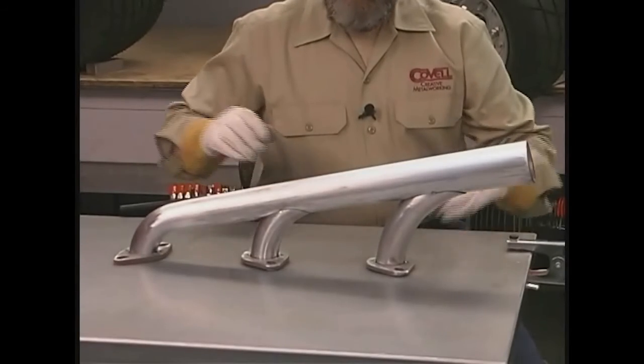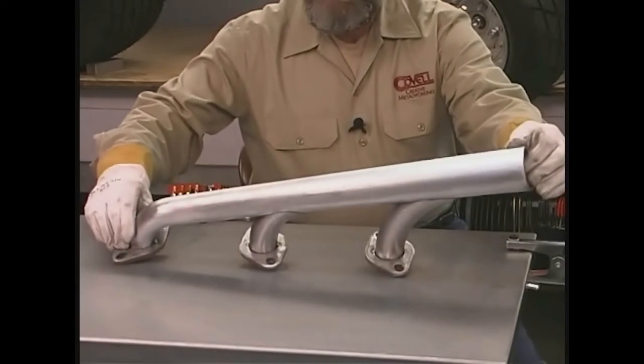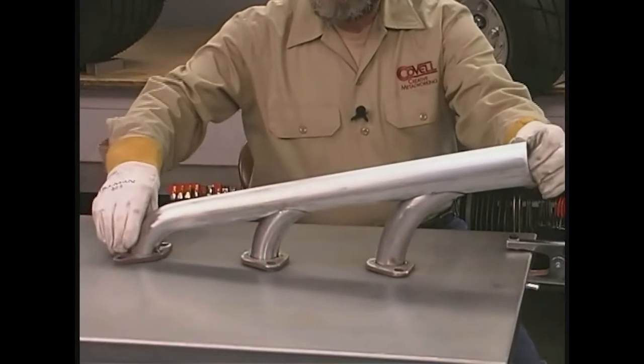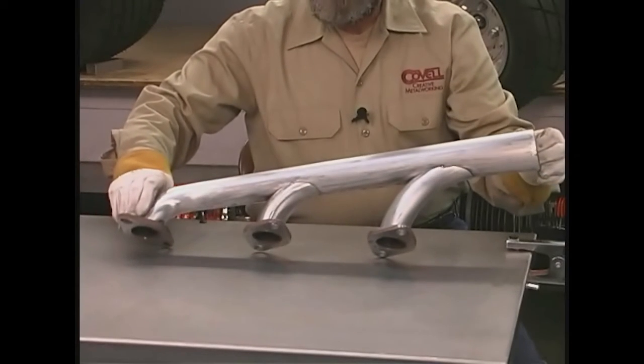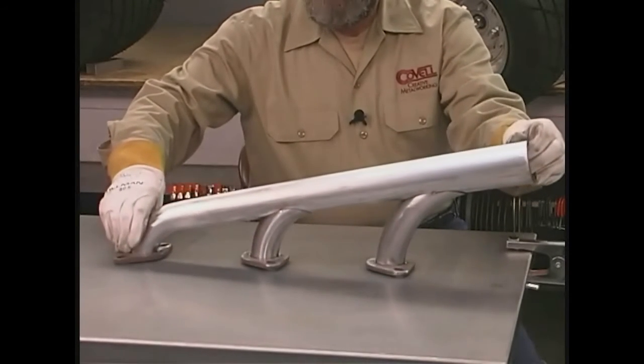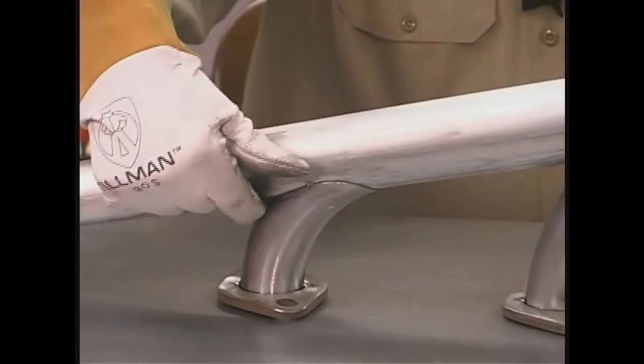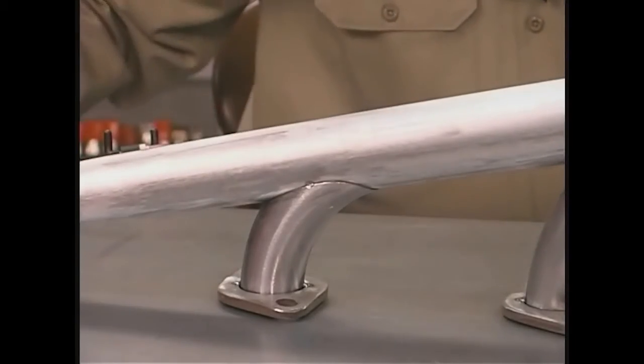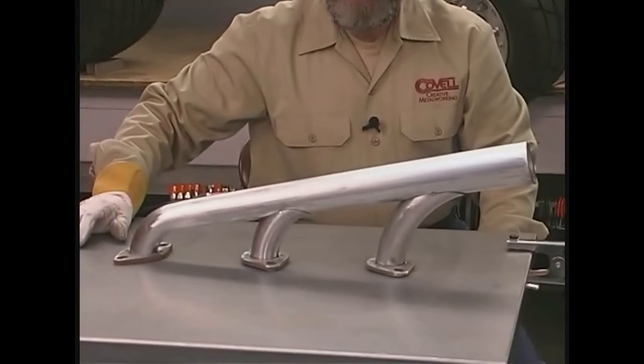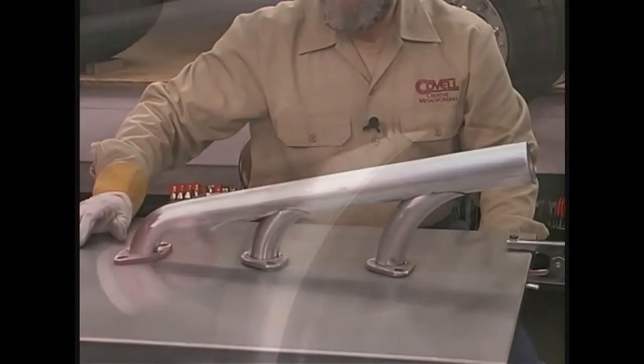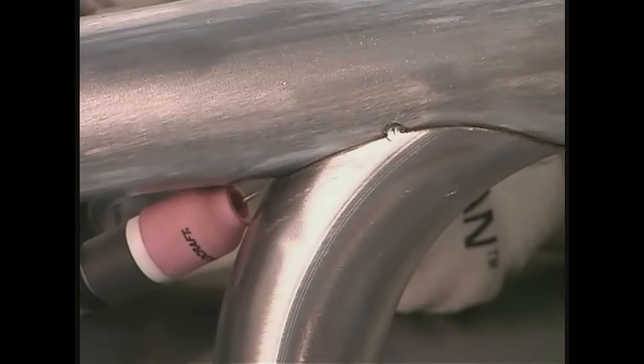Some of the most interesting and also the most demanding types of joints that I've had to work on are those of tubing, where you have complicated pieces of tubing that fit together. It's always a challenge to get a TIG torch into these tight little recessed areas, but it can be done, and I'll show you some of the techniques I use for that. In situations like this, the gas lens is going to be your best friend. And with the tungsten stuck out this far, we actually can get right into that little joint.